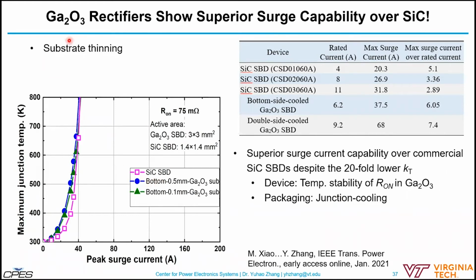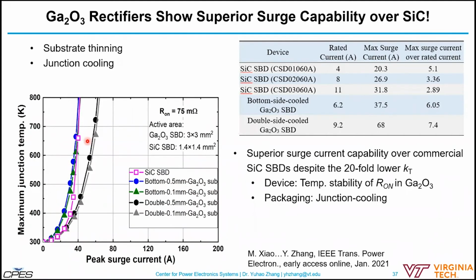The first way is substrate thinning. For example, here shows the maximum junction temperature and the peak surge current. If we use 800 Kelvin, for example, as a standard for the surge current, this is the silicon carbide Schottky barrier diodes. And if we look at the gallium oxide devices with two different substrate thicknesses, there is not too much difference. If we use junction cooling, which is a double-side cooling package, that can provide a strong boost in the surge current capability. Changing the substrate thickness makes no difference, because most of the heat doesn't go through the gallium oxide substrate.